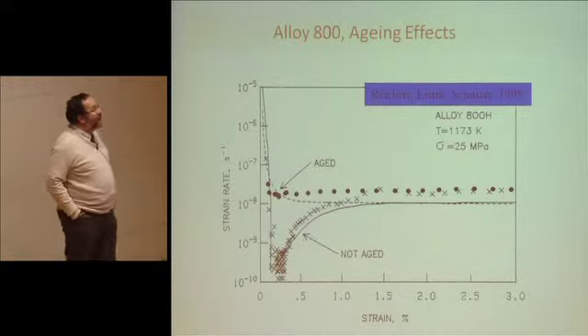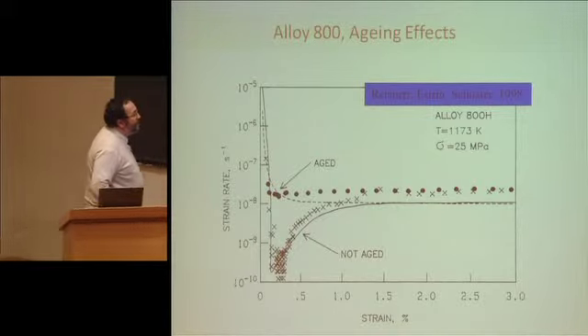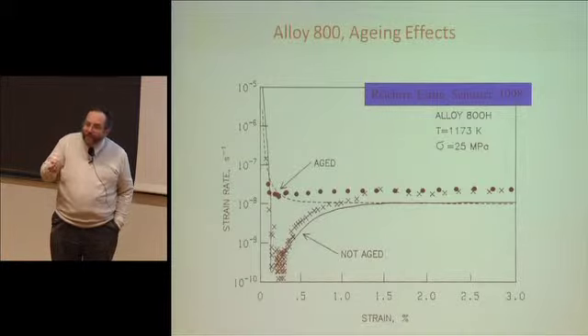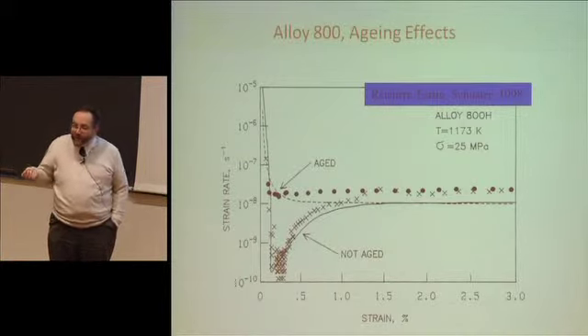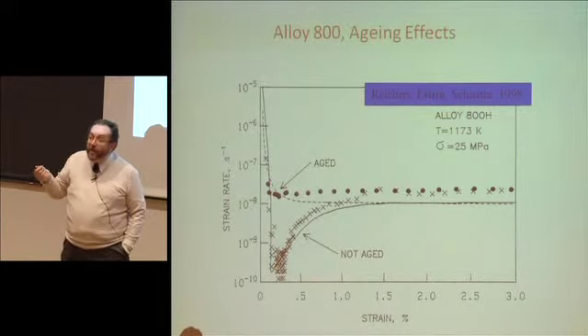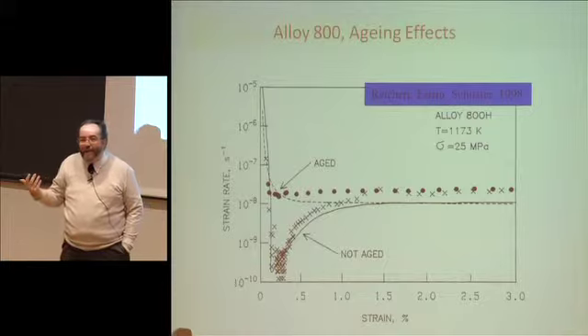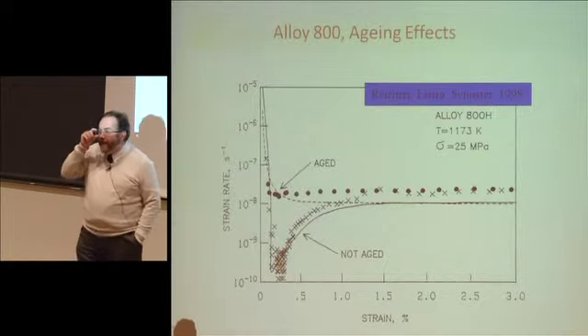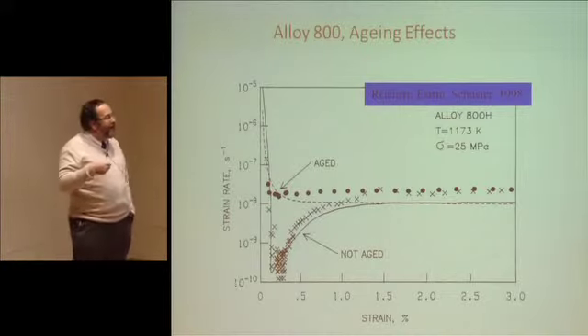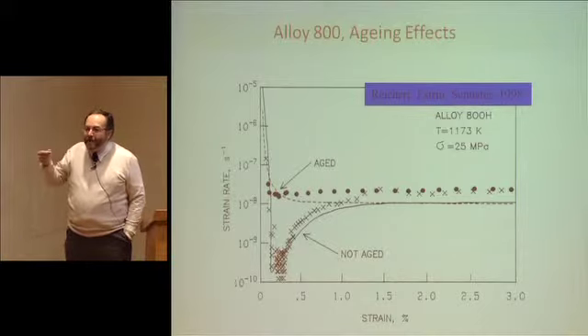So this is one example carried out on an alloy of aging effects. You have deformation speed. The test was carried out with an imposed deformation speed based on that to identify the parameters. You have little black dots here, which are the predicted behavior, creep behavior, based on what was identified in tensile testing. So the hypothesis is that the mechanism remains essentially the same. And then you carry out the same test with a material that is not aged. A material where you have a situation where you can actually precipitate and then coalesce the precipitation state. This is what is done here.